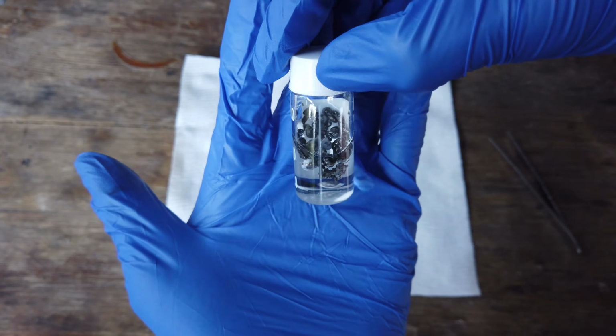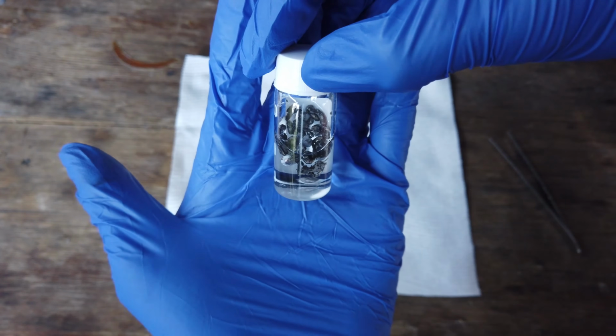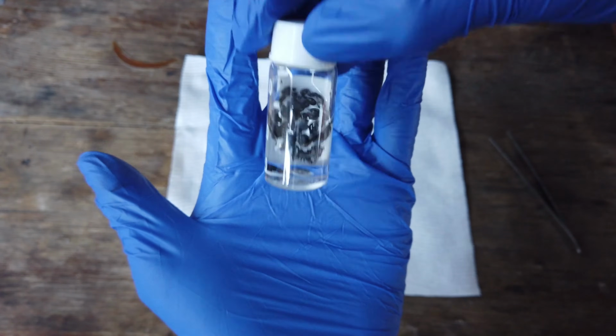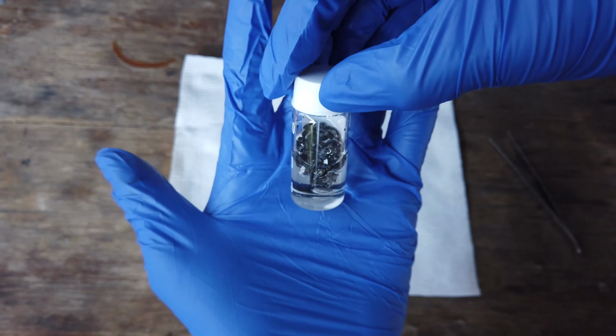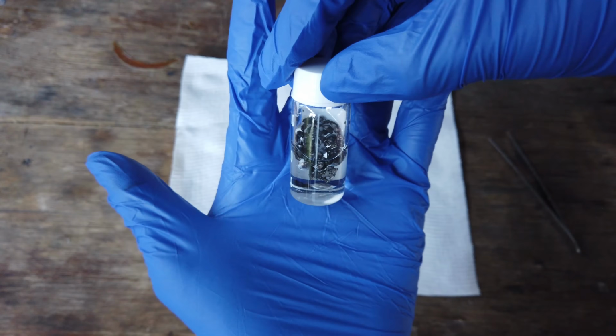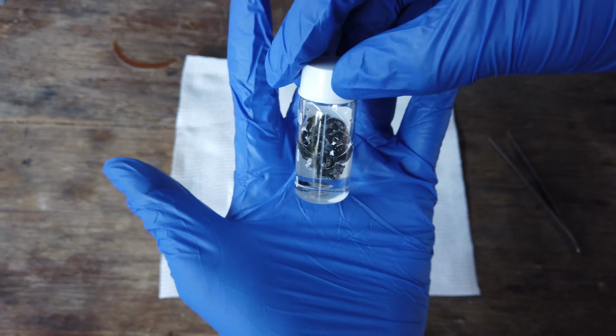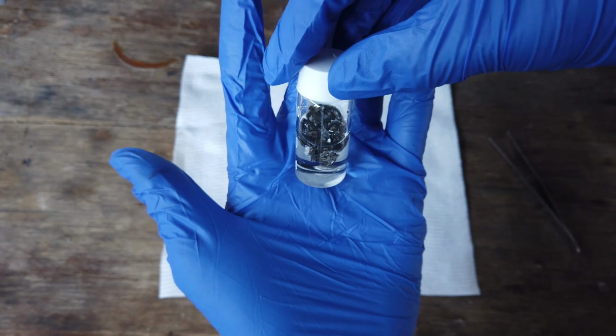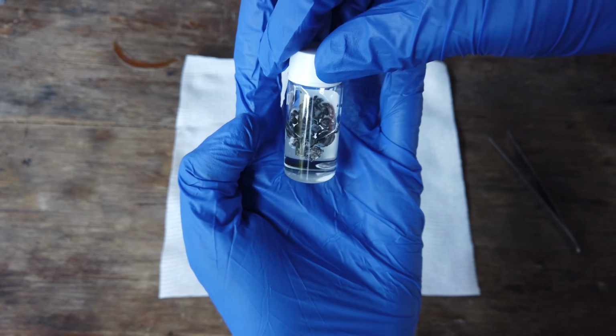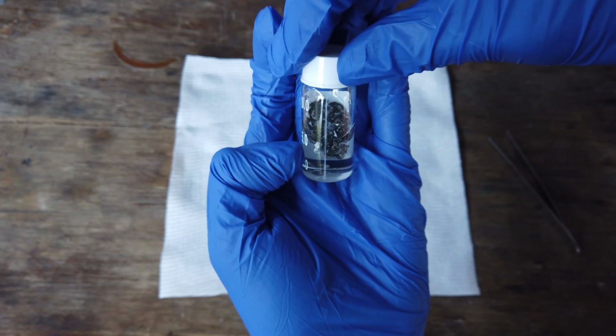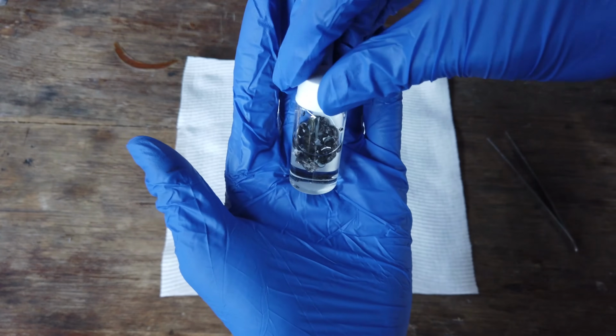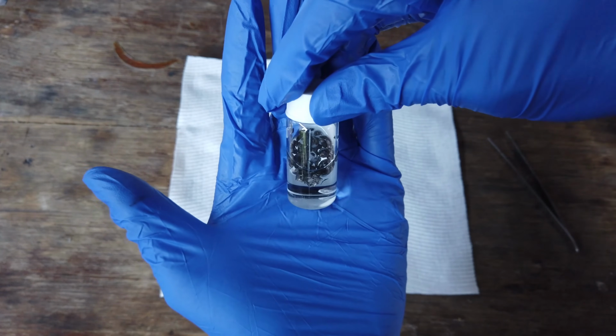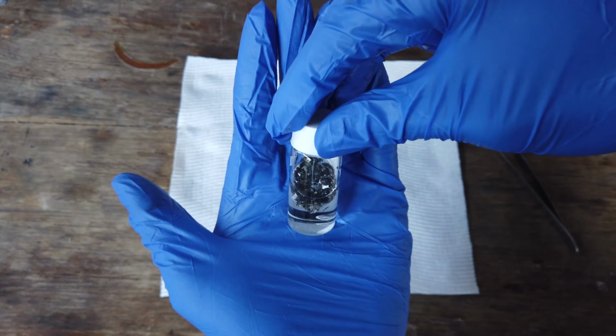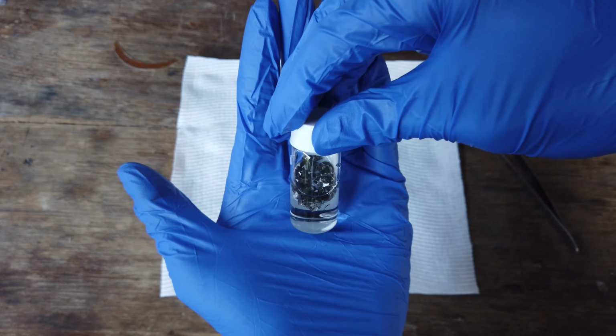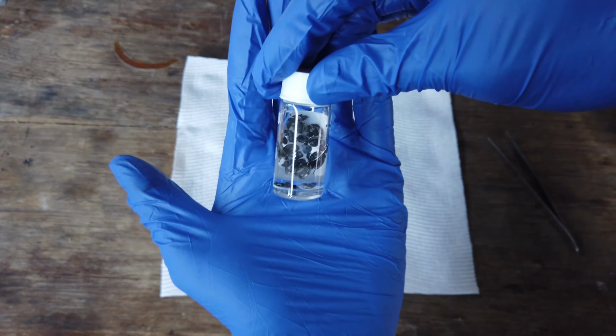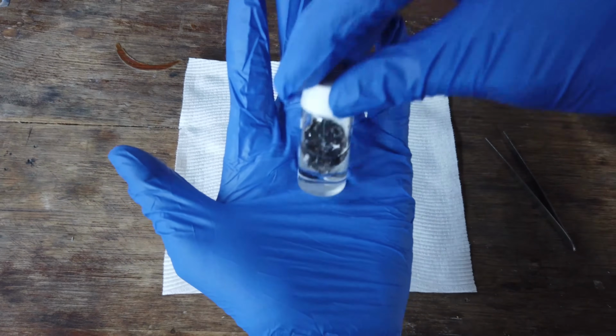Also, our total yield of lithium isn't all that great, at least in terms of mass, because the density of lithium is so low. It's a very not dense element. Is there a word for not dense? I'm not really sure. We have maybe half of a milliliter to 1 milliliter worth of actual lithium metal, which corresponds with less than half a gram. I'm not going to get it out and weigh it, simply because the surface area is really high and weighing it would inevitably oxidize it really quickly, and I really don't want to do that. I want to keep it in this vial. So I'm not going to weigh it, but our yield is probably less than half a gram, which sounds bad, but it's really not too bad because the molar mass of lithium is extremely low. It's only about 6.9, I think, grams per mole. So that's actually quite a sizable amount of lithium that we have here.